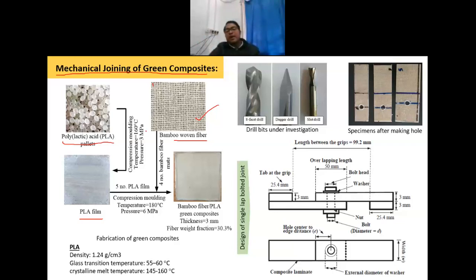Okay, then again we have applied the required amount of pressure and temperature. The temperature that we have applied is 180 degrees centigrade and the pressure is 6 megapascal. At this temperature, the polymer will melt and impregnate into the woven fiber mat, and upon cooling it will solidify and you will get the composite plate. The composite plate that we have fabricated is 3 millimeter in thickness, and the fiber weight fraction we have considered is 30.3%.